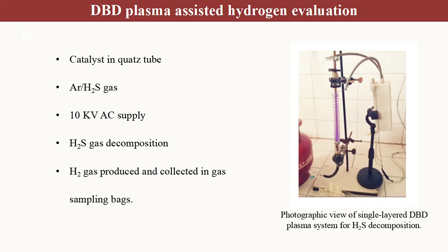The aluminium oxide supported chromium doped zinc sulfide semiconductor catalyst was tested for hydrogen evolution from hydrogen sulfide gas using a single-layer DBD system. The discharge volume of the dielectric barrier discharge reactor was 22 ml.